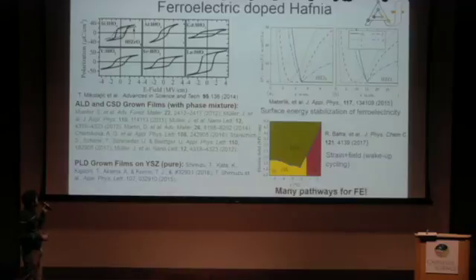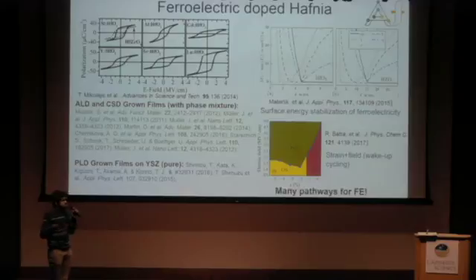However, the problem is that most of these films are polycrystalline and polyphase, so it's difficult to decouple individual effects experimentally and understand what the effect of each factor is on the stabilization of ferroelectric phases. So our strategy has been to design clean experiments where we study the effect of strain by changing the substrates. We study the effect of doping, specifically by choosing the hafnia-zirconia system, because zirconium has the same exact size as hafnium. So putting zirconium in hafnium positions doesn't induce any internal strains, unlike, say, yttrium or lanthanum or some other ions. And also, we can study the effect of point defects in this experimental setup by varying the oxygen partial pressure, for example.